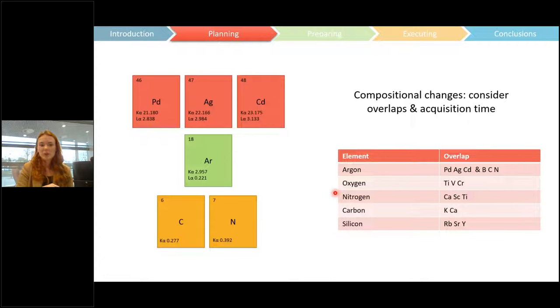But first, I want to talk about the composition, because the composition changes are usually a little bit challenging, especially if you are performing reactions under argon. We often use argon as our dilution gas because it seems to be the most inert, but it also has the most overlaps in EDX. For example, we very silly decided to stick palladium nickel nanoparticles in to try and do in situ EDX. And of course, argon overlaps exactly with palladium, which is a really big problem for us. But it also overlaps quite badly with silver and cadmium. Obviously, there are other overlaps to consider, but the most annoying one we usually find is argon.